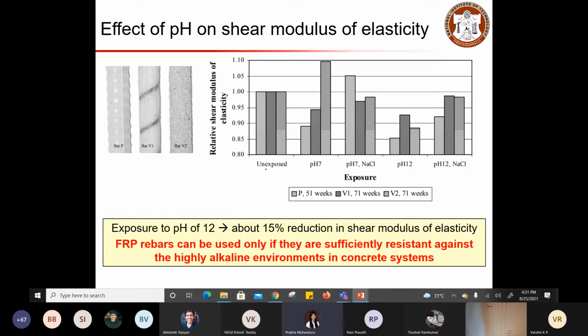Exposed at, so the bar P basically represents 51 weeks, and this one, the gray one, indicates bar V1 type, and then this checked box basically indicates bar V2 type. All these things basically indicate the exposure duration. And when you have unexposed FRP rebar, the shear modulus of elasticity is uniform for all the cases. But when the pH value changes and when the exposure duration changes, then you can see a change in your shear modulus of elasticity. So if the pH value is less, this bar V2 type shows the higher shear modulus of elasticity. As the pH value increases, you see the reduction in the shear modulus of elasticity in this case.